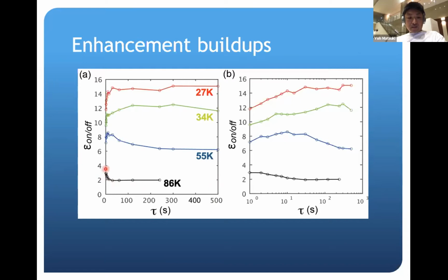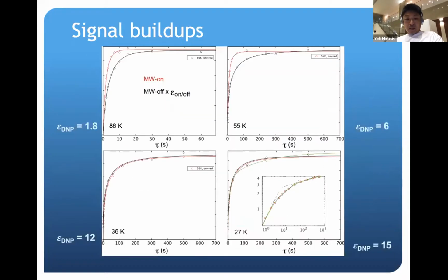It's a very interesting feature we see. At high temperature, you get higher enhancement at shorter time, and at lower temperature you get lower enhancement in the beginning. This is the plot in semilog to look at the beginning part of the curve. The curve is really changing over temperature. I guess this is from a change in the penetration properties as a function of the temperature, because this is the build-up time as a function of temperature, right?